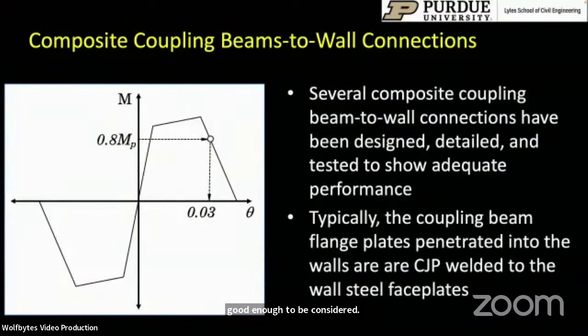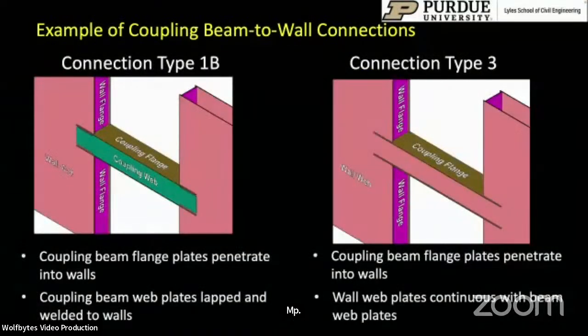Typically, the coupling beam flange plates are penetrated into the walls, and I'll show you a picture of that in just a moment. But the performance requirement for this coupling beam connection is that it should have a rotation capacity of about 0.03 radians before the moment capacity drops below 80% of Mp. So that's the performance requirement for this coupling beam to wall connection.